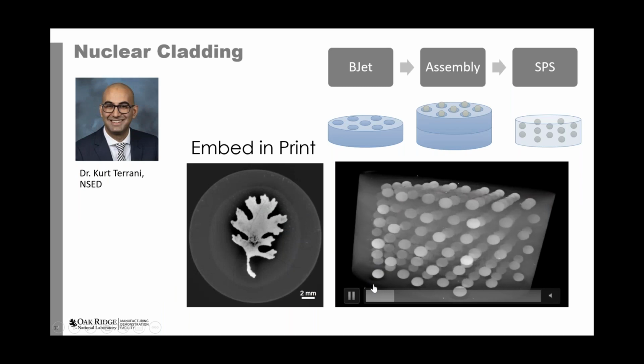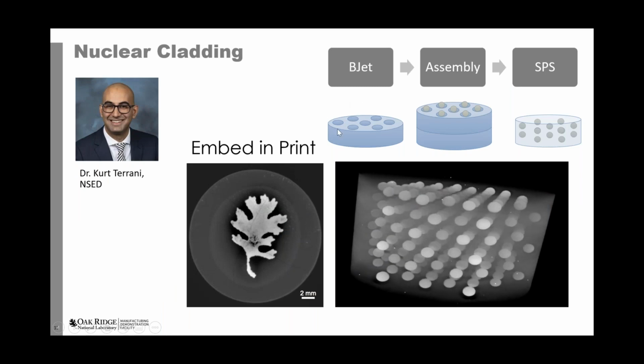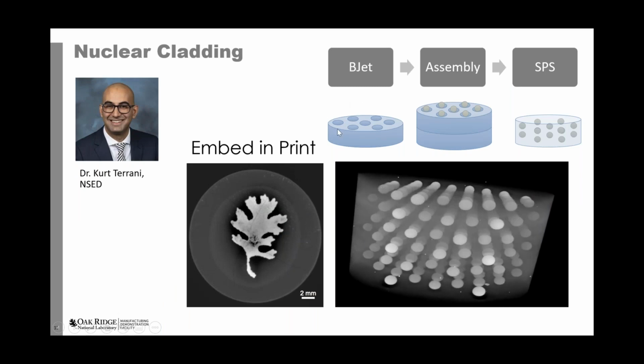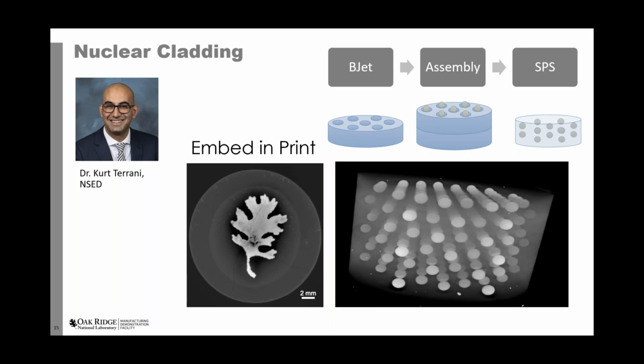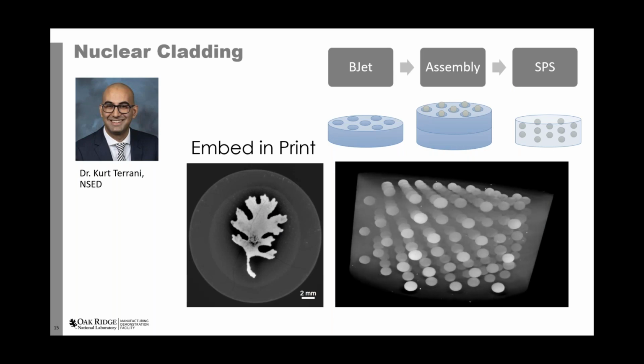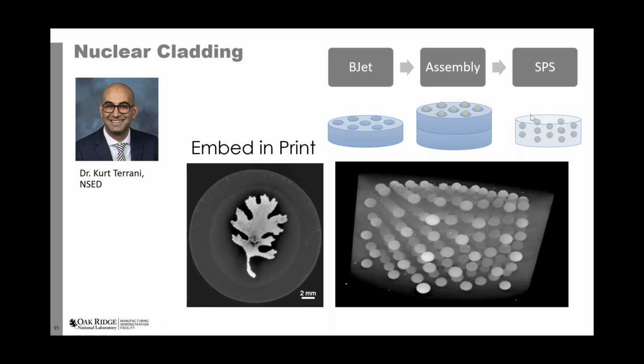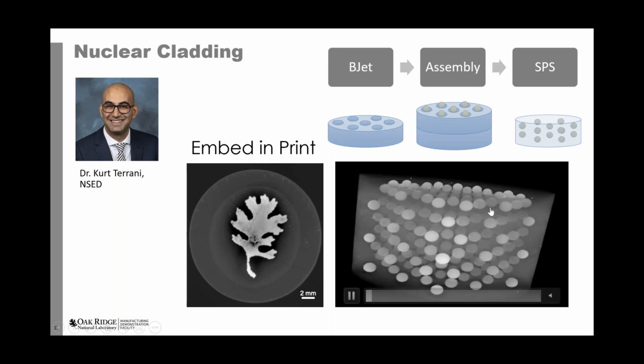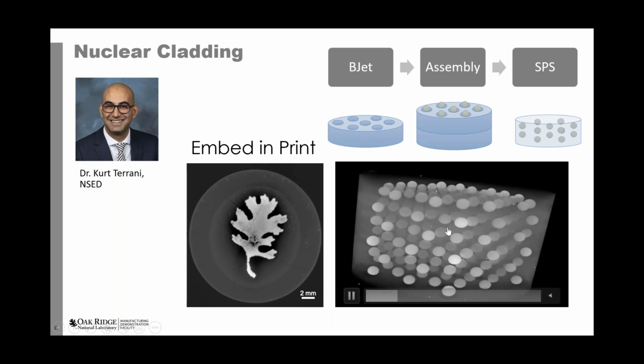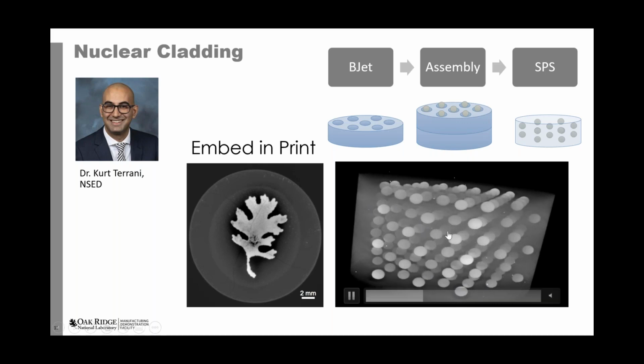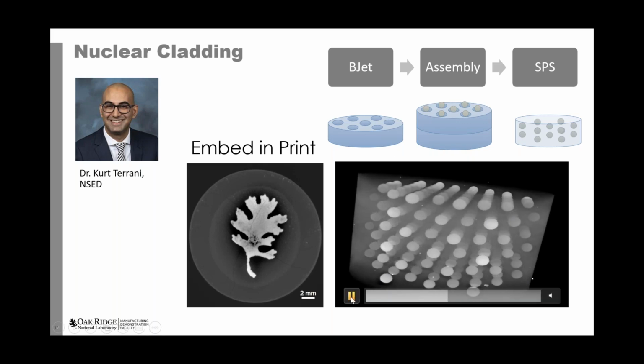And then this is one of the cooler videos where we've shown that you can print something like silicon carbide and we've inserted these surrogate fuel pellets into the silicon carbide, and then used spark plasma sintering to consolidate the silicon carbide around the pellets, and shown that you can make a really uniform distribution of fuel pellets using binder jetting.